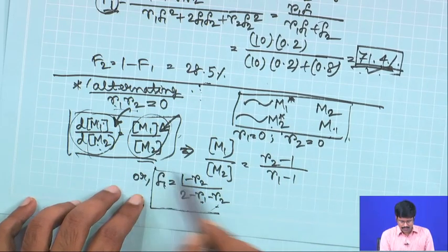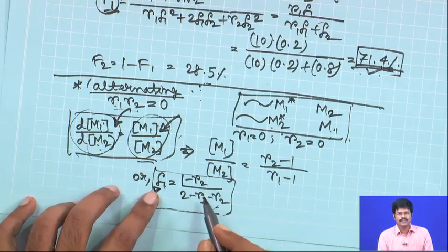So, if you take this mole fraction for monomer 1, then for that particular composition of the co-monomer feed when you are copolymerizing, your copolymer composition will remain exactly the same as the co-monomer composition. So, this is your azeotropic copolymerization. Remember, both r1 and r2 values have to be less than 1. Otherwise, that curve of capital F1 versus small f1 will never cross the capital F1 equals small f1 straight line, which indicates that the composition of the copolymer is equal to the composition of the comonomer mixture.